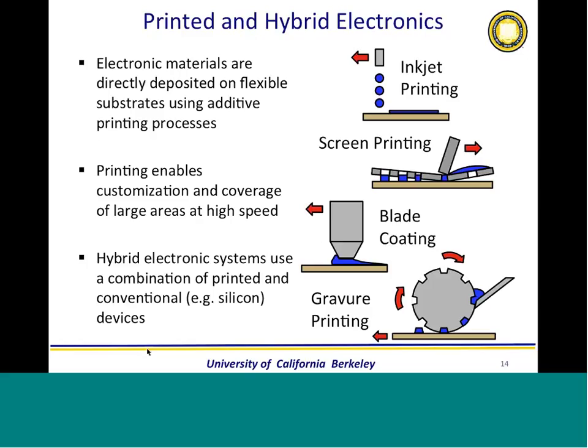We also use a lot of screen printing because screen printing is so easy. My student built a screen printer for $100. And you buy the screens from shops that are making silk screens for T-shirts. And then as you develop the relationship with them, they become interested because you're printing electronics, and you can actually get screens that are quite good. The resolution is about 50 microns with screen printing, and quite thick film, so you can get good wires, let's say.